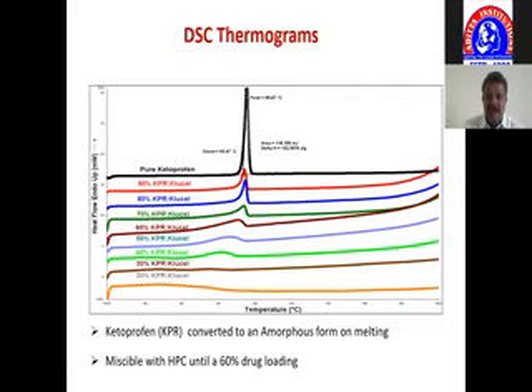Now, when I'm combining the drug with polymer, what you see is, as I keep on reducing the drug concentration from 90% to 20%, that is the drug loading, I'm not able to see any melting point of the drug. So typically at 30% and 20%, you are seeing the total peak has been abolished. This indicates that we have converted the crystalline ketoprofen into amorphous ketoprofen.